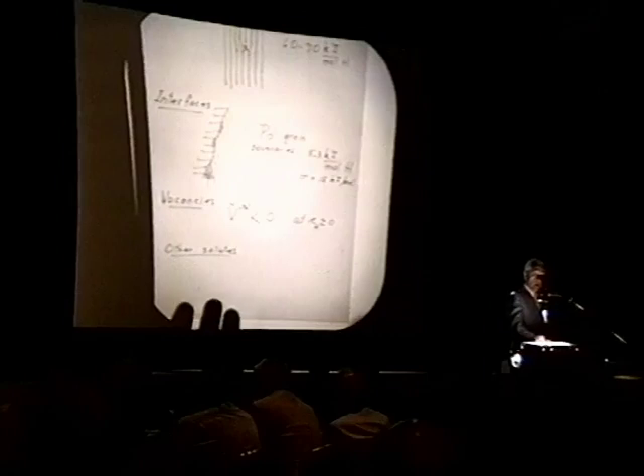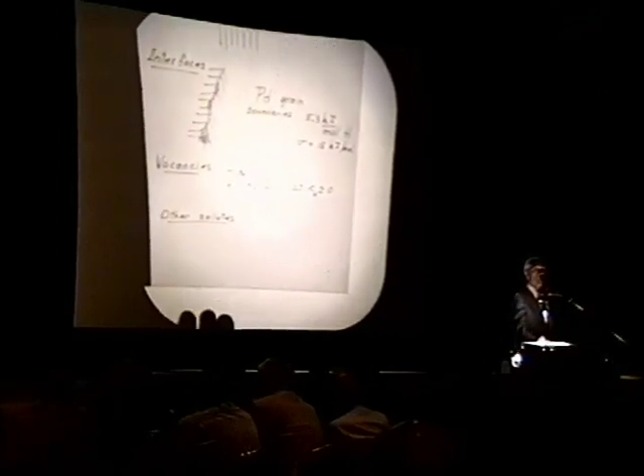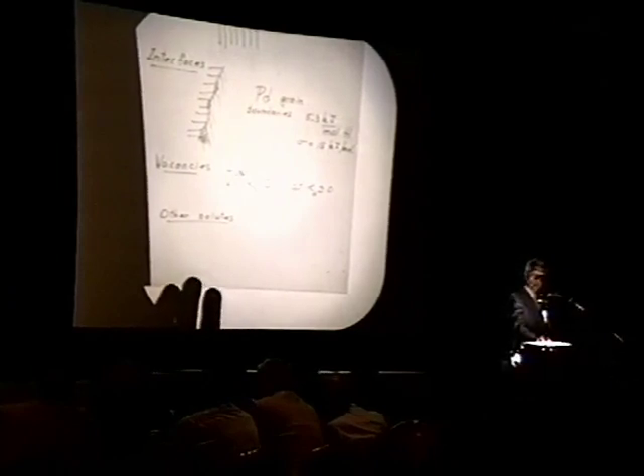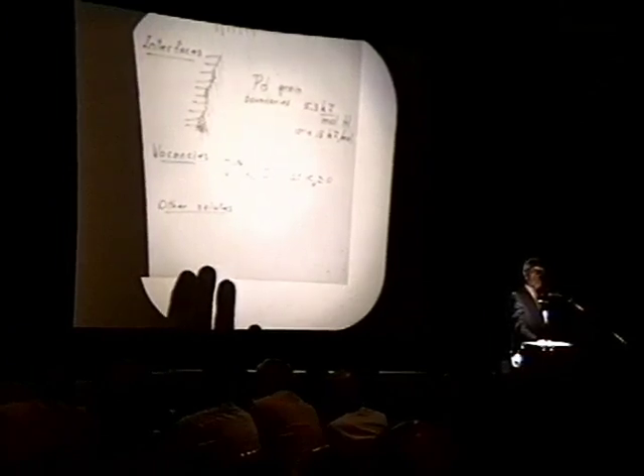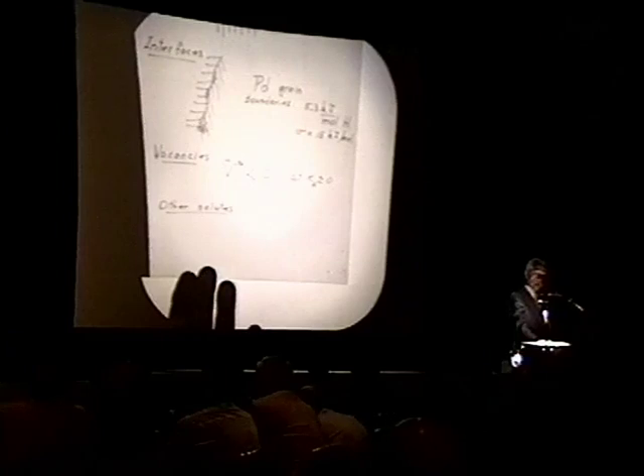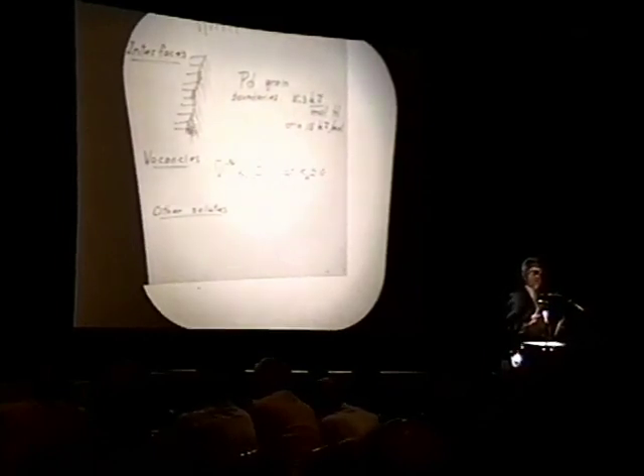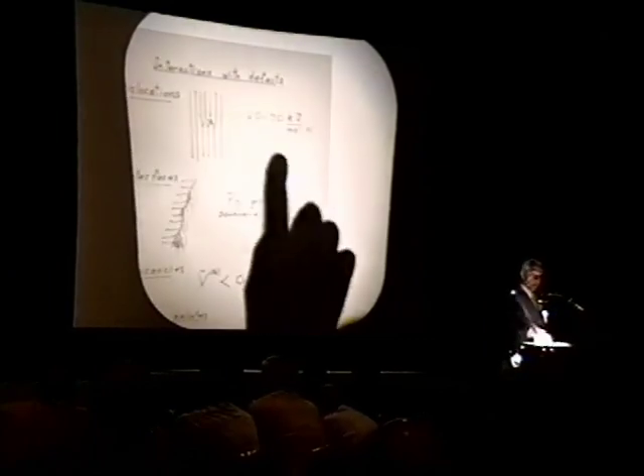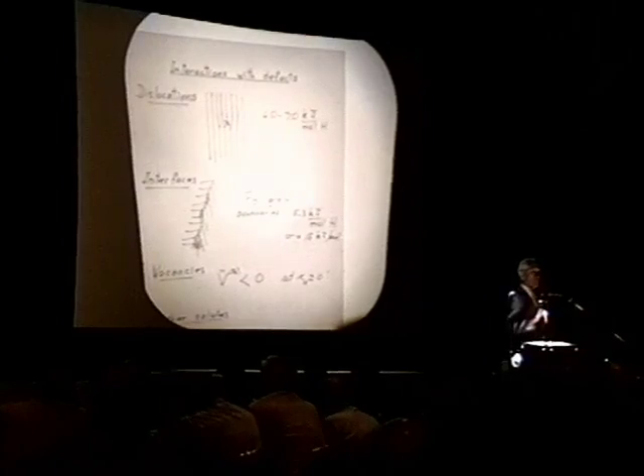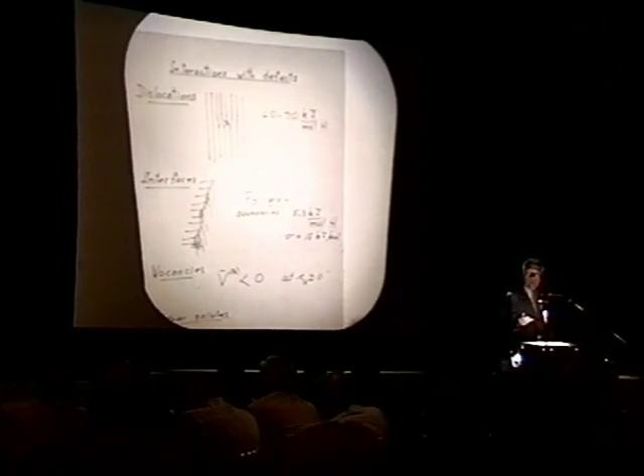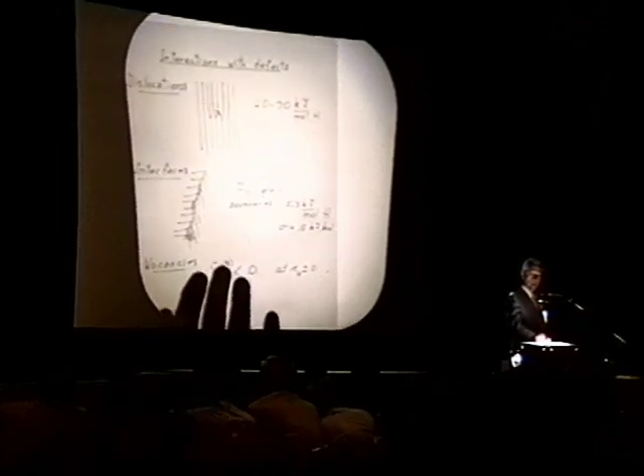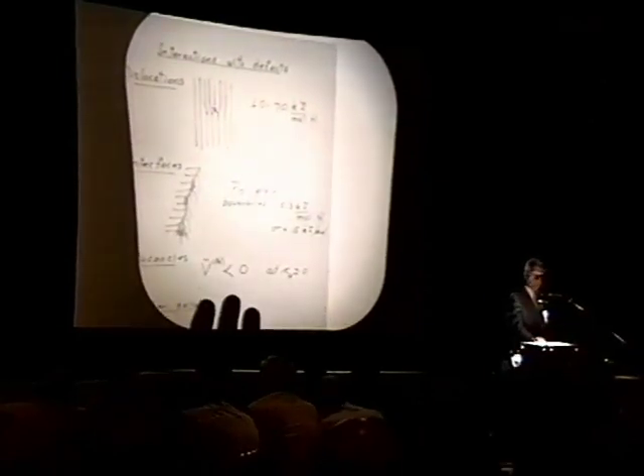A vacancy in palladium, rather amazing to me, has the highest interaction energy with dissolved hydrogen. This is an inference, as I mentioned yesterday in the discussion, made from measurements by Kirchheim of the partial molar volume. When one introduces an extremely small fraction of ppm of hydrogen in palladium, he found that the partial molar volume is a negative quantity. The thing shrinks instead of expanding. The only way to understand this is that the hydrogen enters adjacent to a vacancy. And we already see a large interaction energy with dislocations, but by virtue of the fact that the first bit of hydrogen that is injected must go into an even deeper trap, we see a negative partial molar volume. That means, therefore, that the interaction energy must be larger than this, and I yesterday gave an offhand estimate of about 100 kilojoules.